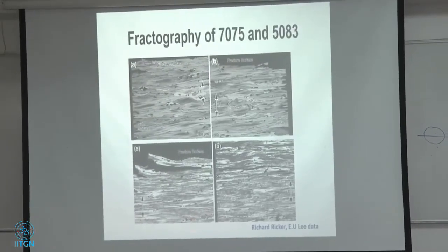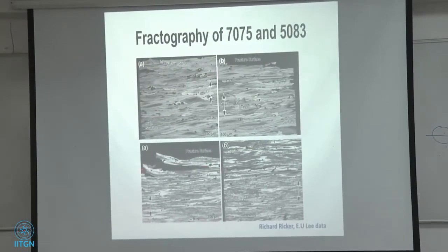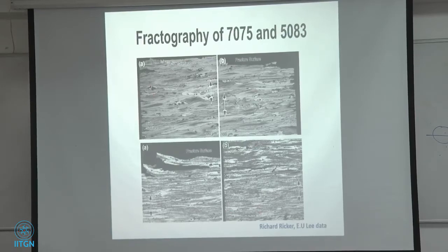This is 100 microns, 0.1 millimeter. You can see that's a pretty long crack right underneath the fracture surface. And you can also see there is a crack right there beneath the fracture surface. Okay? This is for 7075, this one.